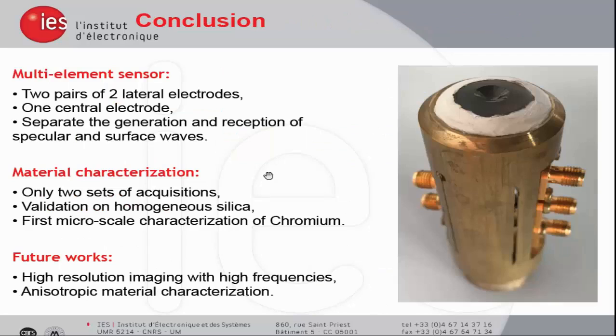So to conclude, we proposed a multi-element sensor with 2 pairs of lateral electrodes and 1 central electrode to allow separate generation and reception of the specular wave and the surface Rayleigh wave. This allows the material characterization and imaging thanks to only 2 acquisitions, so that reduces greatly the time of reconstruction of the image. And this was validated on silica and first applied to the characterization of a chromium sample.